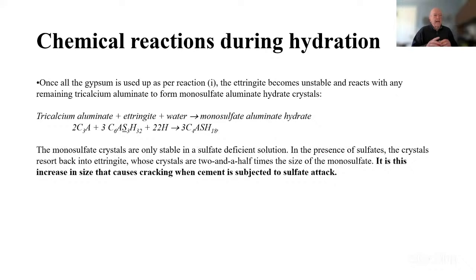Okay, so this is the last one that I think is important, and it's kind of interesting as well. So the tricalcium aluminate, we talked about it. Its first reaction that occurs, it forms these monosulfate crystals, and you can read like I can. They're only stable in a sulfate deficient solution. So in the presence of sulfates, the crystals will revert back to ettringite. So as soon as the gypsum is used up, the ettringite starts to disappear. Okay, it sort of dissociates, and that's a good thing, because that ettringite is a fairly large structure,